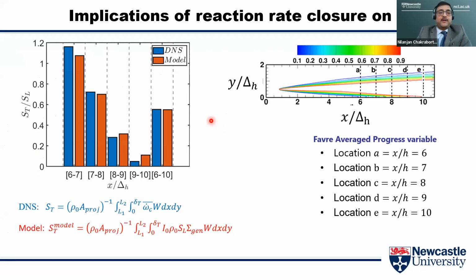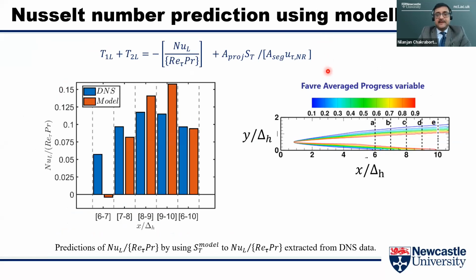The implication of that model inaccuracy is that if we look for turbulent flame speed between these two zones, these two zones, and these two zones, there can be local discrepancies. The discrepancy is relatively high close to the leading edge of thermal boundary layer, because thermal boundary layer starts around this region. But when you integrate from 6 to 10, they are in reasonable agreement. Now, once we understand that, this is the integrated form of the energy integral equation. And if I put the S_T from the DNS data, I can get these blue values for the normalized Nusselt number.